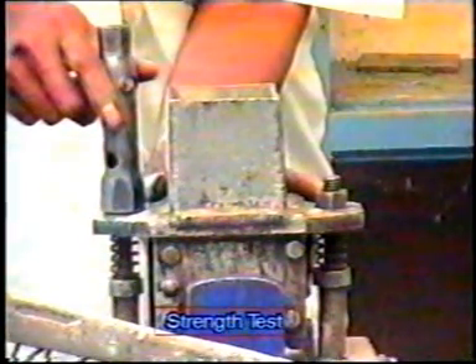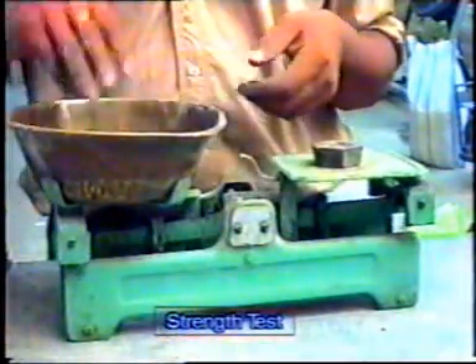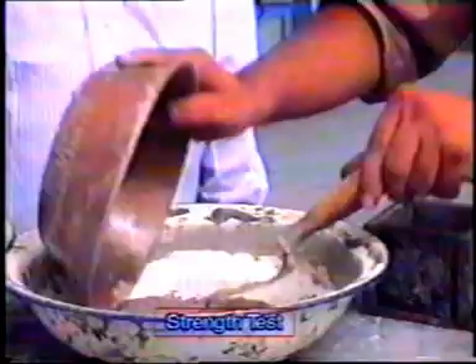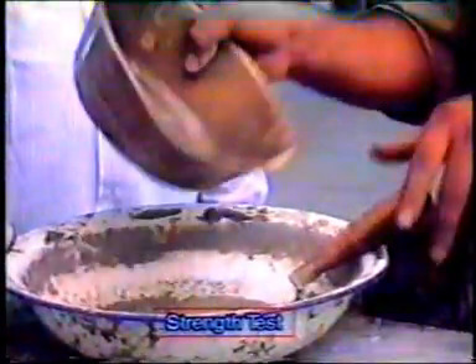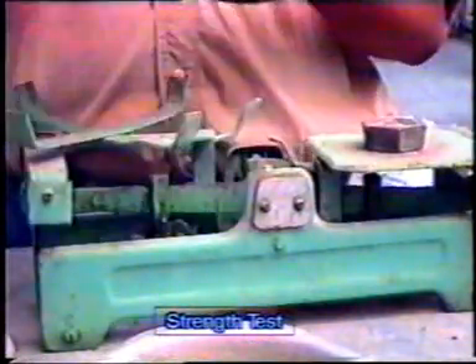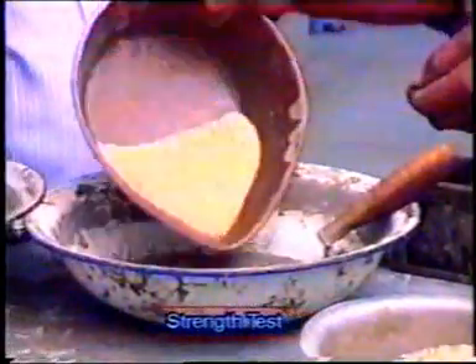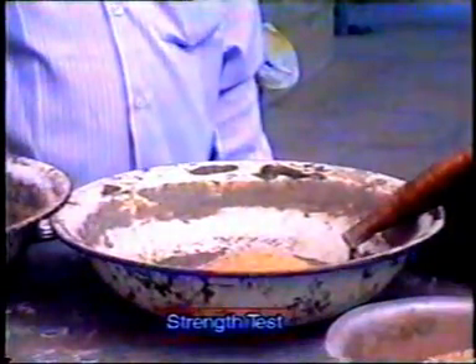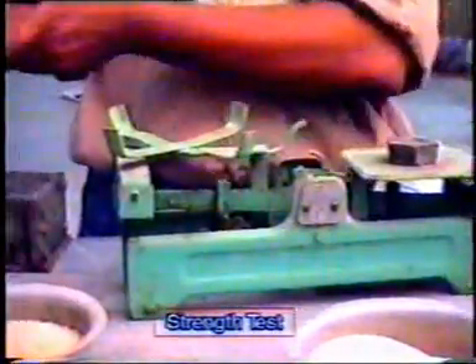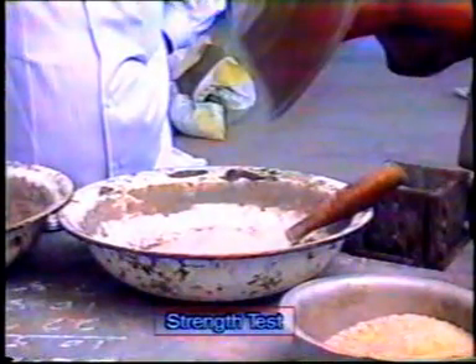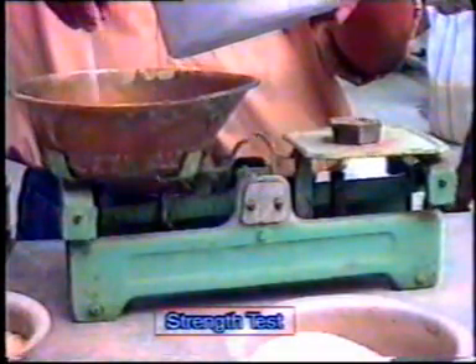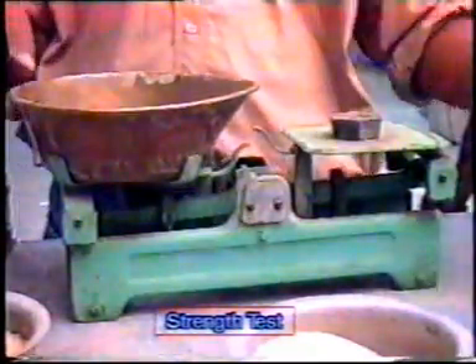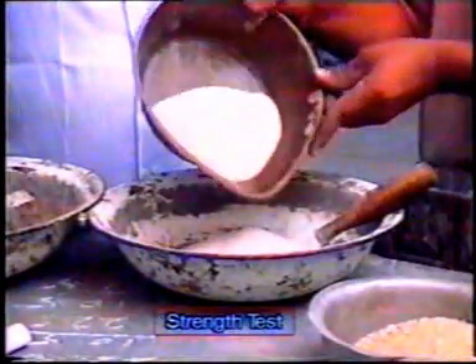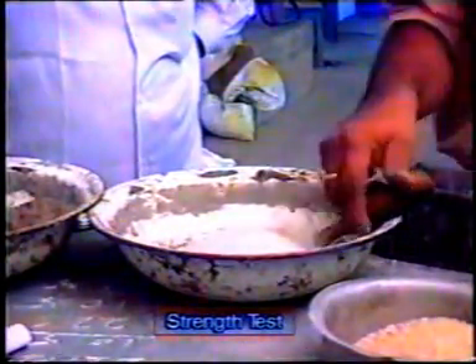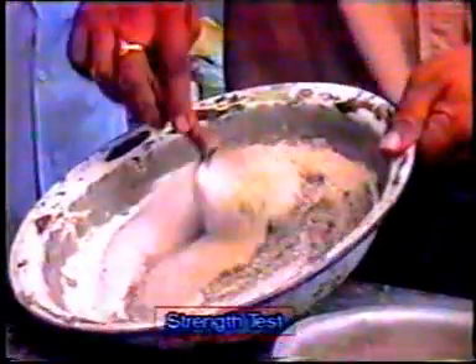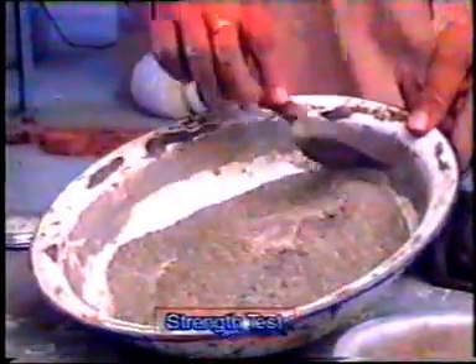Now, place the sample of cement 200 grams into the mixing dish. Take 600 grams of sand, duly mixing sands of grade 1, grade 2, grade 3 in equal proportions. Total of 600 grams of sand is taken. That is the proportion of 1:3 by weight. Add water to the mix.